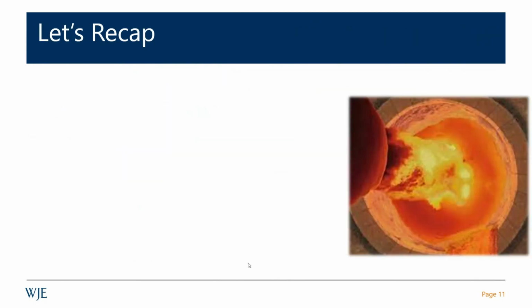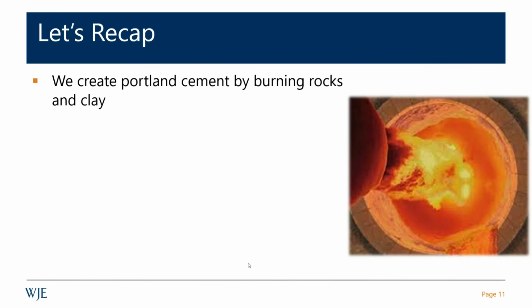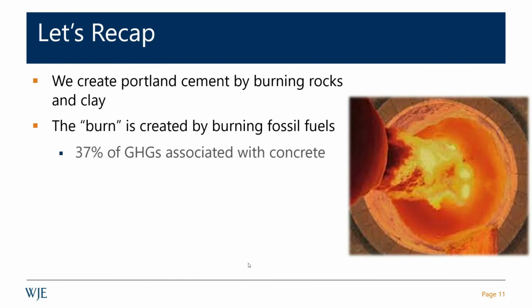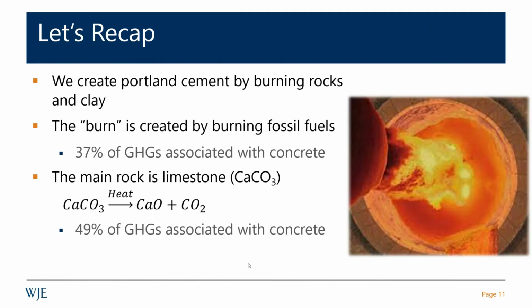So just recapping, we make Portland cement by burning rocks and clay in a kiln at very high temperature. That kiln is using fossil fuels to create the burn, which is roughly responsible for 37% of the greenhouse gases associated with concrete, not just cement, but with concrete. The main rock, though, that we're burning is calcium carbonate. And if you look at that very simple chemical equation, and I promise you it's the only one in this presentation, you're seeing that we're decomposing calcium carbonate into calcium oxide, lime, and CO2. And that driving off of that CO2 is responsible for almost 50% of the CO2 in concrete.